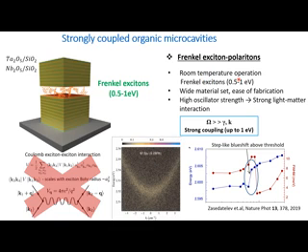But the dark side, let's say, of the Frenkel excitons is their small exciton Bohr radius. Therefore, Coulomb exciton-exciton interaction is not present anymore. But nevertheless, in the vast majority of experiments, we observe blueshift phenomena. With increasing energy density of polaritons in the system, we see that the energy of polaritons increases as well, as you can see here. So it just increases with the increase in pump power.